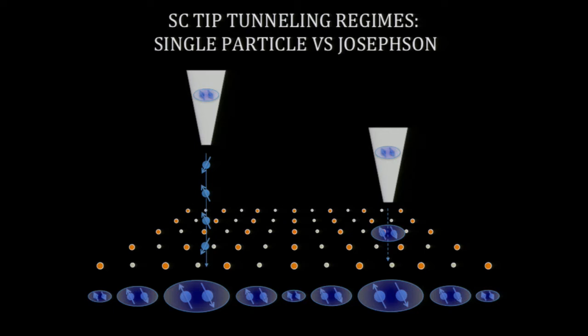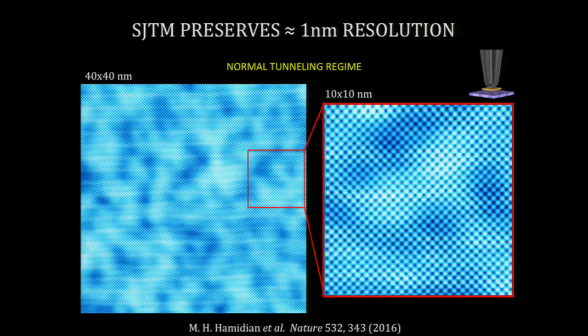What you really need to do is to push this tip in pretty far, such that the overlap between these 2 wave functions allows for a Cooper pair to tunnel between the 2. This is the Josephson regime in which one can actually tunnel Cooper pairs. And this is the normal tunneling regime. And we're actually going to use both. This is actually important for our studies.